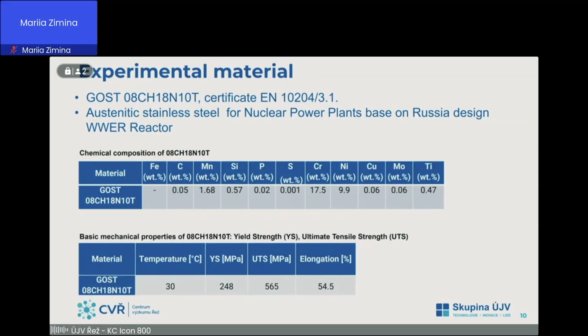Okay, we used two base materials, experimental materials. The first one is austenitic stainless steel, GOST 08CH18N10T. Austenitic steels stabilized by titanium with certification 3.1. It's a certification for application in nuclear power plants.